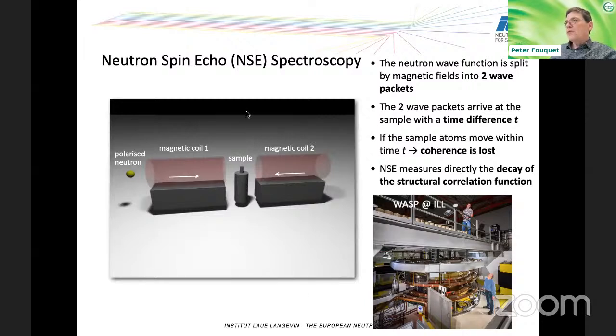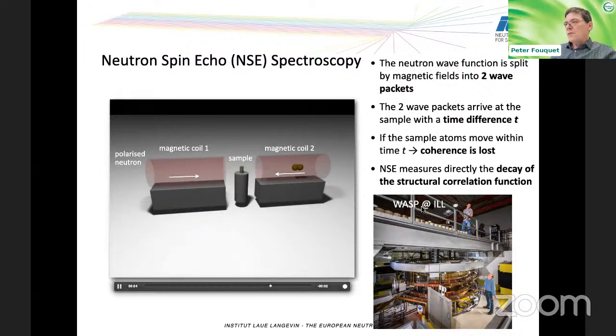Now, a last technique that's very specific for neutrons. And that's the spectrometer where I work, the spectrometer WASP at ILL. There we do a very high resolution technique by exploiting the neutron spin. And we expose this spin to a magnetic field. And with this magnetic field, we split up the wave function of the neutron in two parts. These two parts will interact with the sample with a time difference t, and then recombine in the second half of the spectrometer with an opposite magnetic field.